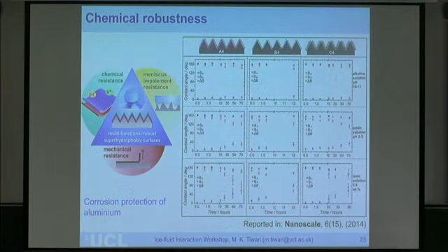This is made out of aluminium. So I told you that other forms of robustness are key as well. So this is a surface where on aluminium we introduced this kind of surface texture by etching, and then we coated them with polymers, and what we showed is that these surfaces are able to take alkaline and acidic solutions as well as ionic solution. This is supposed to reproduce seawater, 3.5% salt, done in controlled lab conditions, granted. And we see that some of these are beginning to have reasonable performance as far as the laboratory sustainability with respect to chemicals is concerned.